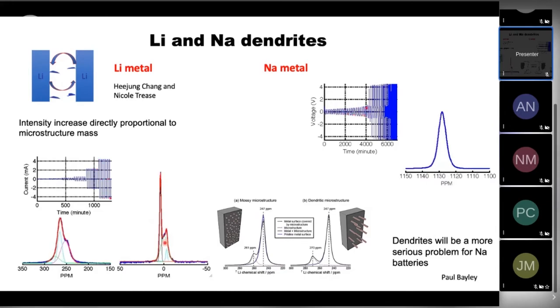And so not only are lithium dendrites a safety issue, they also consume lithium in the cell, forming this inactive phase on top. And so that is another reason for capacity fade. And on the right, at the same time, the movie that's been going on is the same thing for sodium metal, where you're watching the formation of sodium dendrites, even at very low current densities.